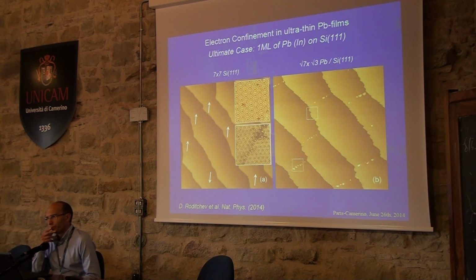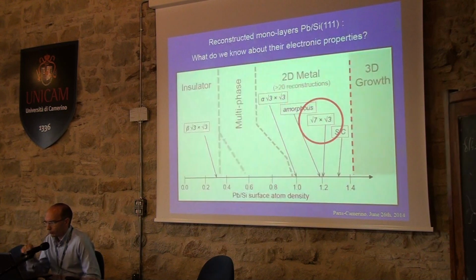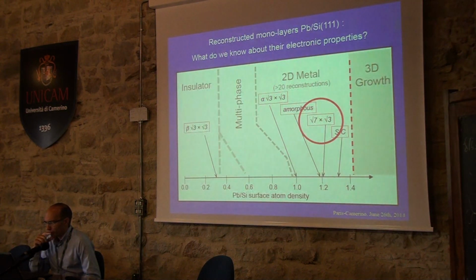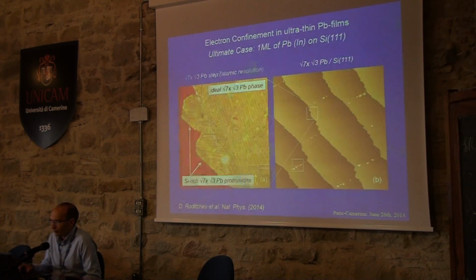And on the right panel, you see the same material, the same sample, covered with a single atomic layer of lead. And what you see is that near the steps, the corrugation increases. Please, next slide. And this corrugation is due to the formation of some particles in which you have a mixture of lead and silicon atoms. Next slide.